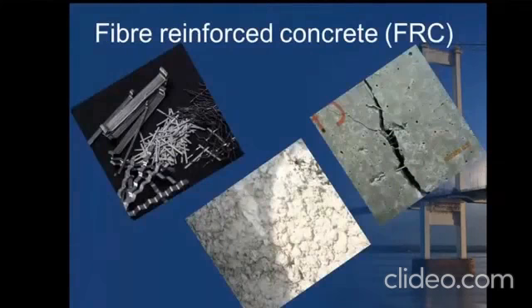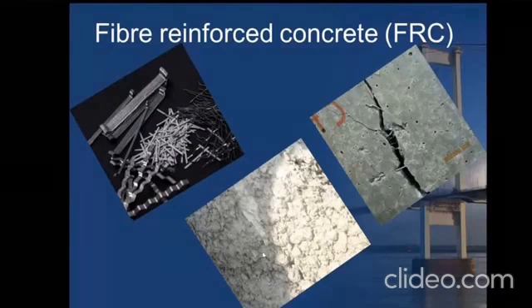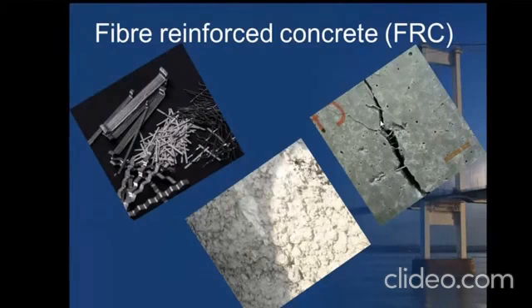So next thing will be fiber reinforced concrete. With fiber reinforced concrete, the major advantage is that it actually bridges the crack. So you could see the images. The first image gives the types of various fibers that are used here. And this is actually the fiber that is incorporated. This is a fresh concrete state where you can see the distribution of the fibers across. And this is hardened concrete after the strength test that has been performed, where you can see the fibers bridging the gaps of the concrete.